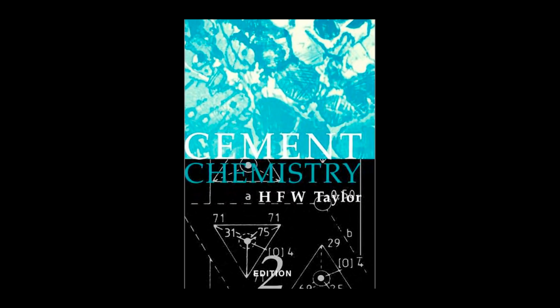And it's chemically advantageous. It is, because it reacts with the calcium hydroxide produced by the OPC hydration, lowering the overall CH content and generating additional CSH, which is known as a pozzolanic reaction. And how does it handle that problematic magnesium oxide? The magnesium in the slag is inherently benign. It doesn't form the expansive periclase. Instead, it forms a phase called hydrotalcite, which is a stable, non-expansive layered double hydroxide. This contributes to better sulfate and chloride resistance compared to just a pure OPC.